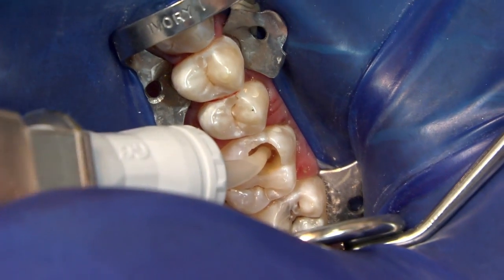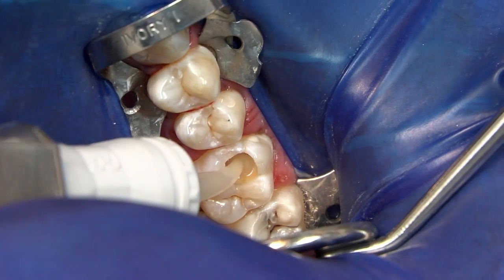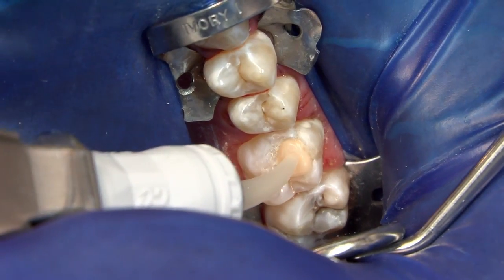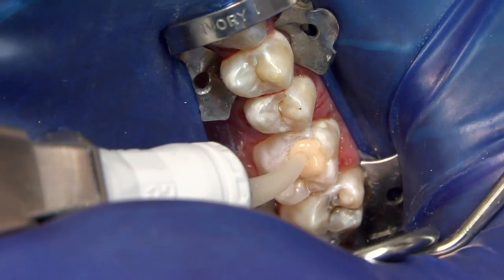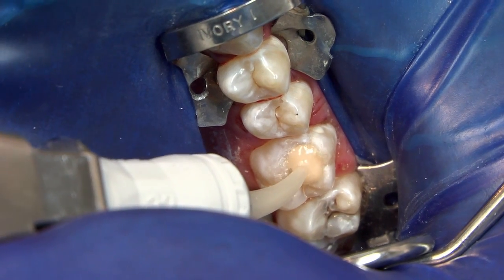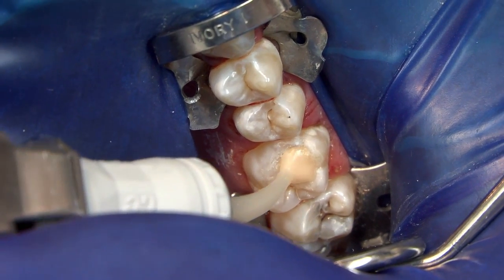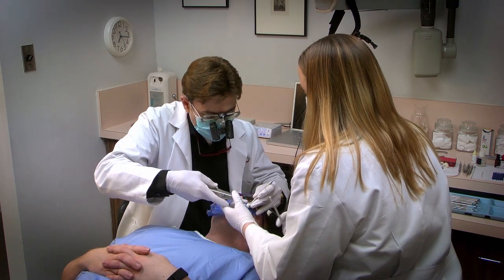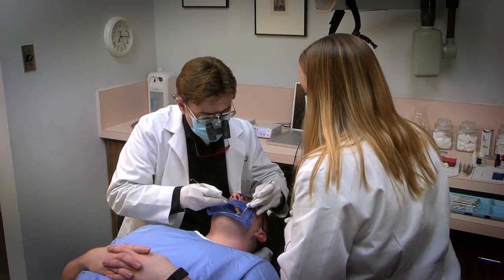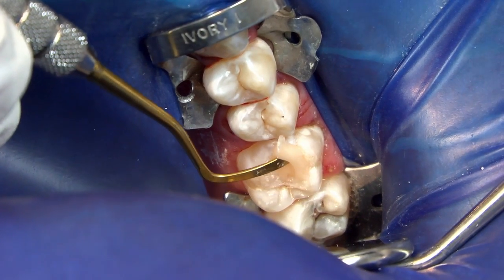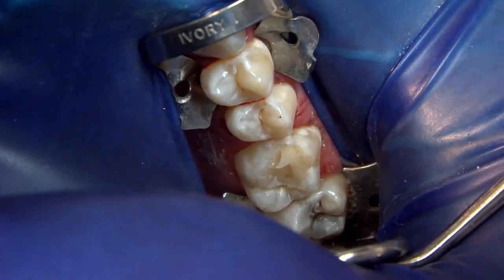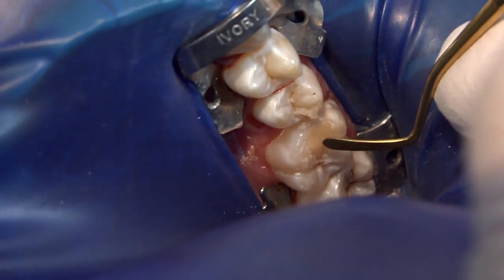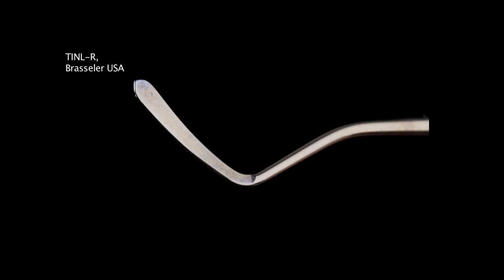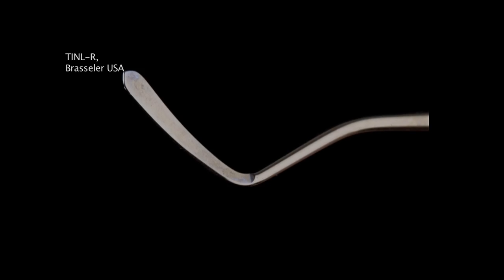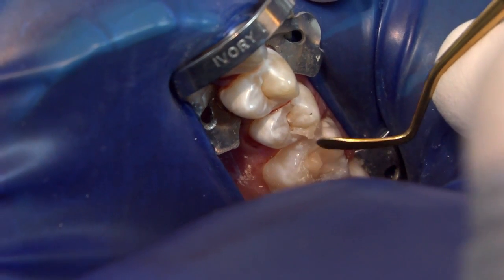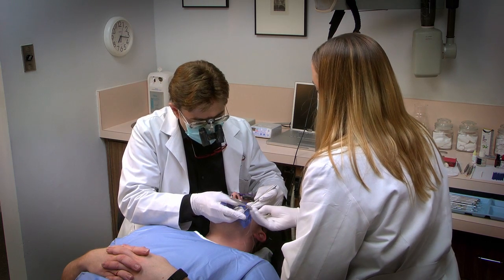Place the Fuji IX GP Extra capsule applicator tip to the base of the preparation and slowly extrude the material to the occlusal surface while removing the tip slowly. This technique prevents incorporation of voids. The material is condensed and the anatomical contours are developed using a curved instrument, a TINL-R by Brasseler, to quickly and easily contour the occlusal planes.